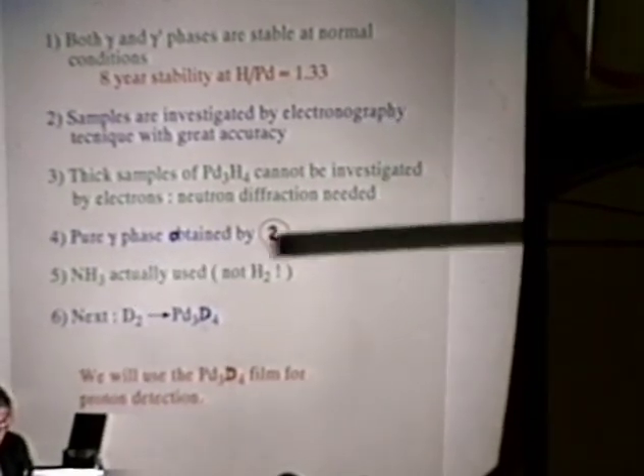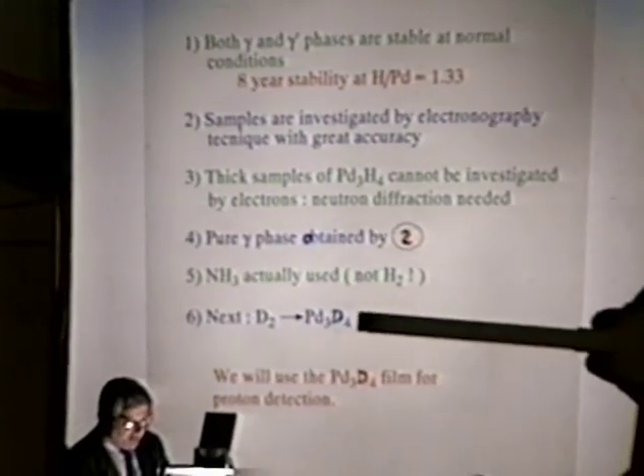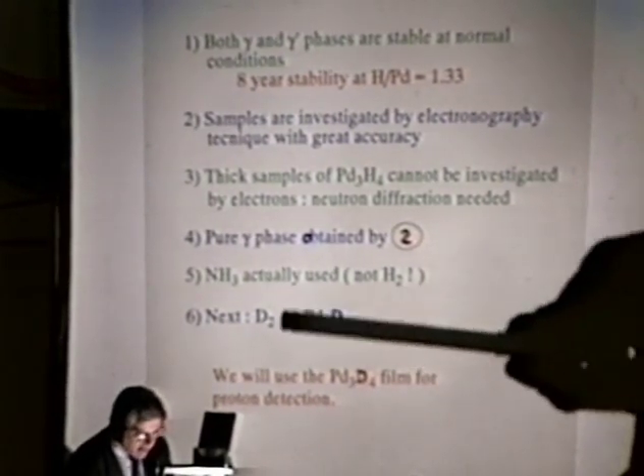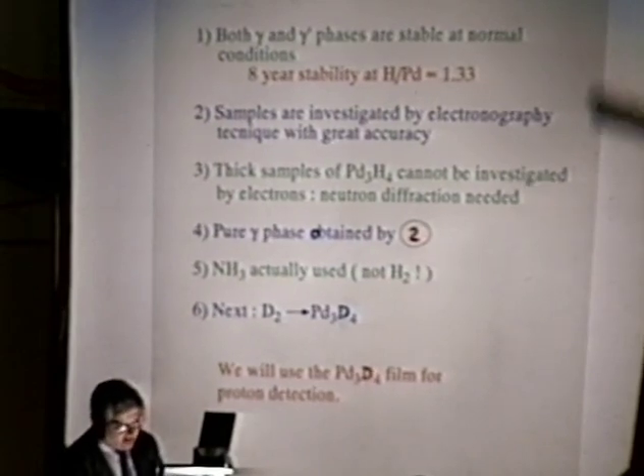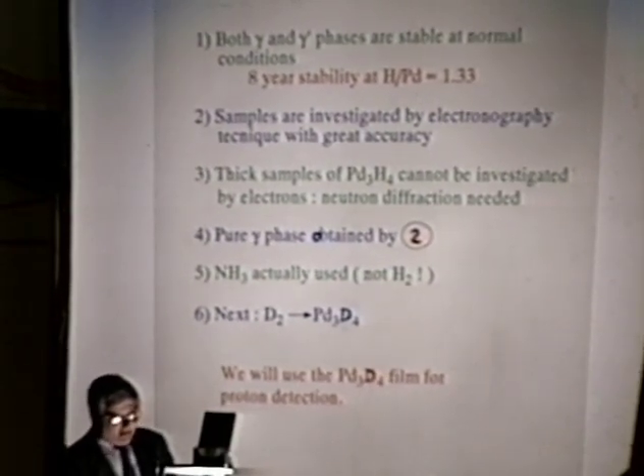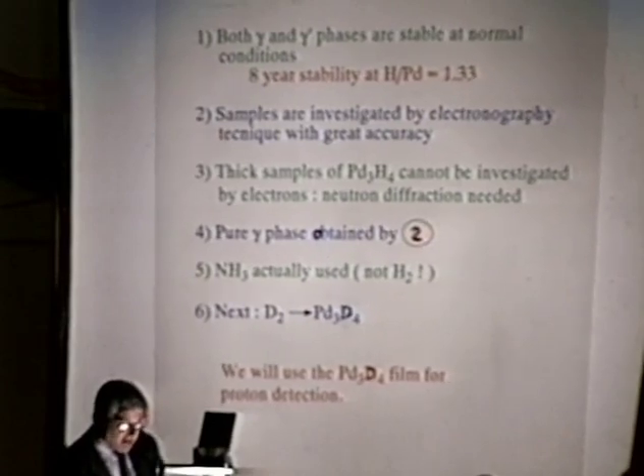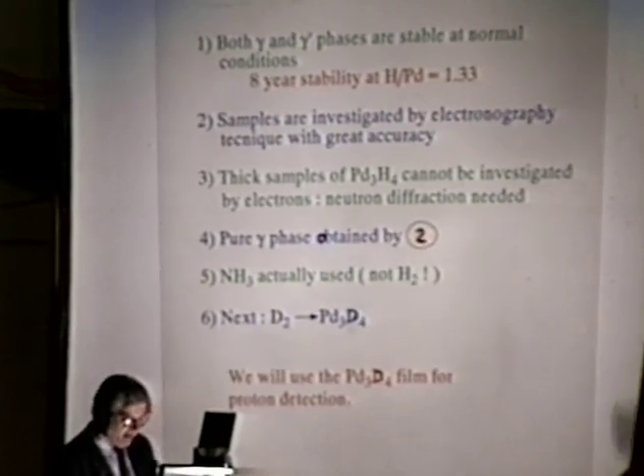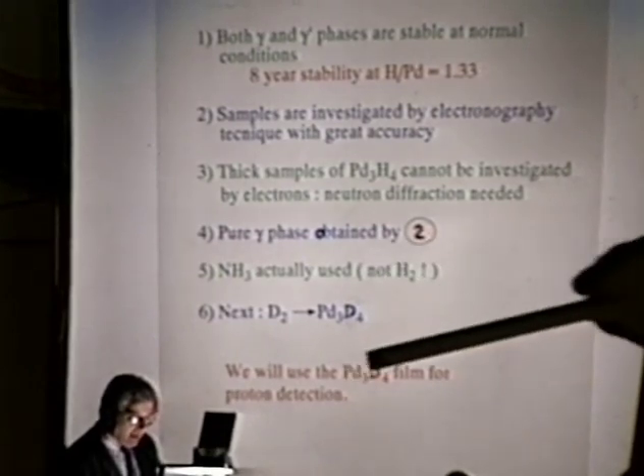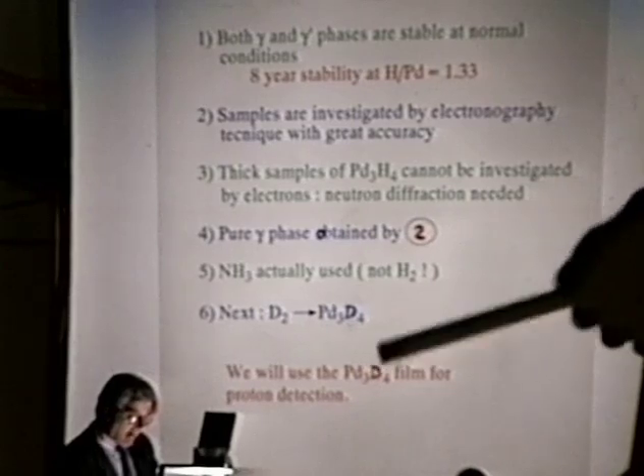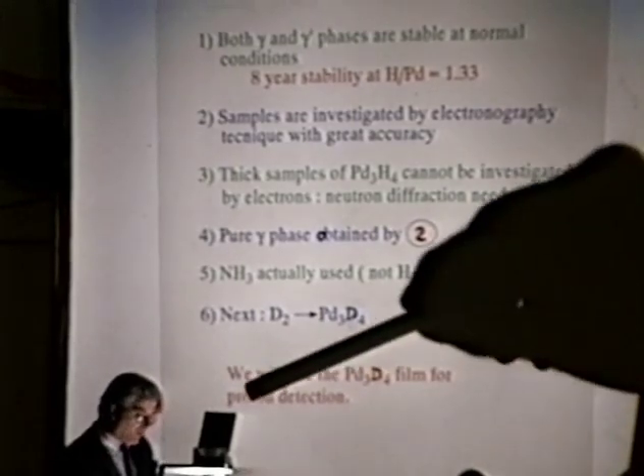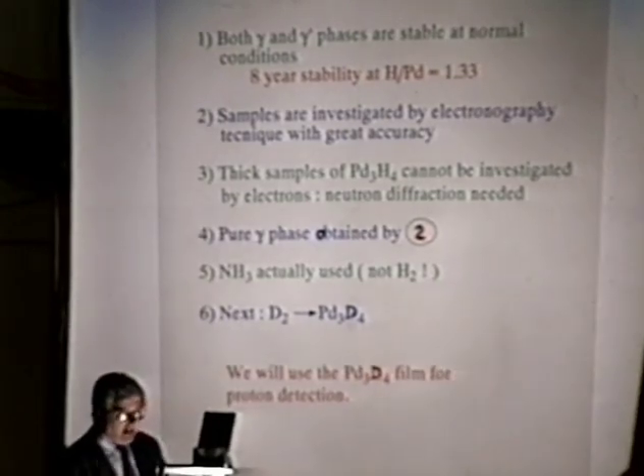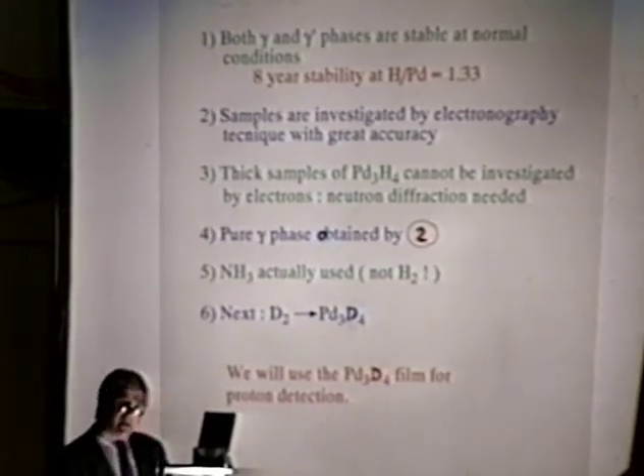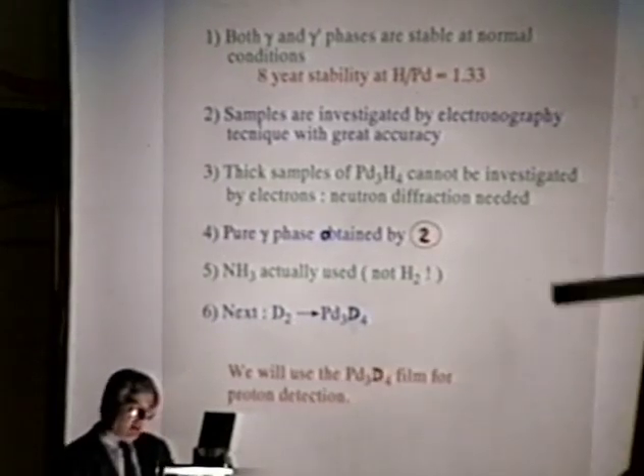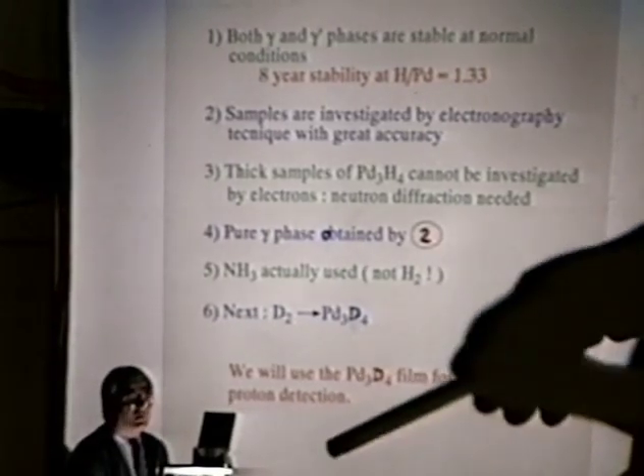And what we will do next will be to use deuterium to achieve this compound, hoping to get the same features. At the end, since these samples are very thin, I repeat, 100 angstrom, we will use these heavy loaded samples as thin films to detect not only protons, but light nuclei. So now you see the correlation between thickness and proton detection, heavy loading and proton detection, and nuclear detection.